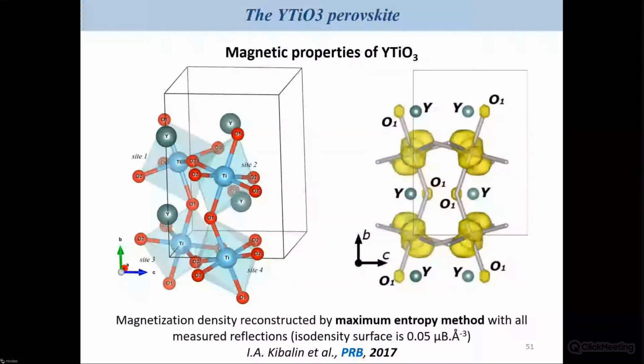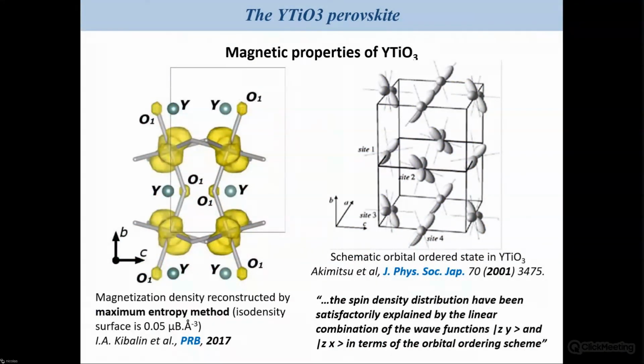It's possible to obtain a good representation of the spin distribution using the maximum entropy method, again, based on polarized neutron diffraction experiments. And this is what we did, and this is the result presented on the right part of my window. You see the shape of that distribution, and it's completely in line with what has been described previously by Akimitsu and co-workers, who indicated that the spin distribution has been satisfactorily explained by the linear combination of the wave functions Zy and Zx in terms of orbital ordering scheme. But in that case, they force the system to be modeled by that kind of combination.